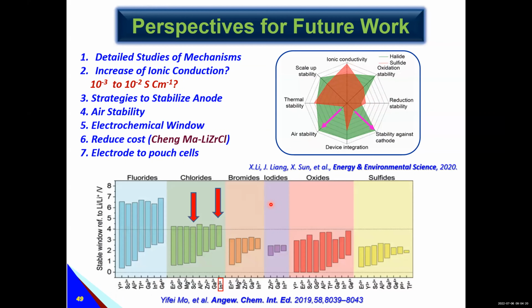Actually, from Professor Mo's calculation, we know how to do it. Currently, we work on a chloride system. You can see the electrochemical window. This one is not close to 0 volts. So that's why it's not stable with lithium metal. But other systems, like fluoride, are much better. So that's why we need to continue to have a wider electrochemical window. One is high voltage with the cathode, and one is low voltage with the lithium metal.